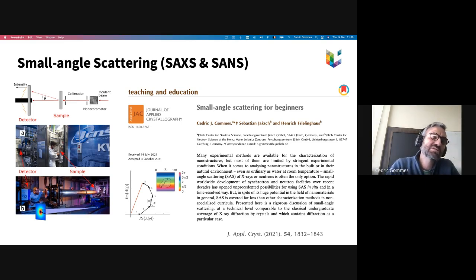So in both cases, the setup is the same. You're sending an incident beam on the sample, and the experiment is essentially similar to X-ray diffraction, only you're measuring extremely small angles. To some extent, small angle scattering is like analyzing the fine structure of what you might consider the direct beam going through the sample in classical X-ray diffraction experiments. And if you want to resolve these very small angles, you have to put the detector very far from the sample. That's why you have these long tubes in both configurations.